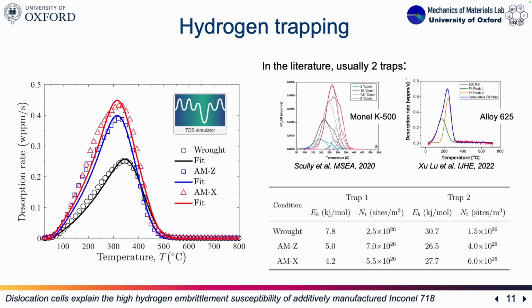But our guess is that this binding energy is associated with the lattice diffusion in this Inconel microstructure. And then we have a higher energetic trap that we think for the wrought is associated with grain boundaries, or these carbides and nitrides that are interfaces we have in the grain boundaries. And then for the AM, a trap that corresponds to the interfaces of this dendritic, cellular structure, or the walls.